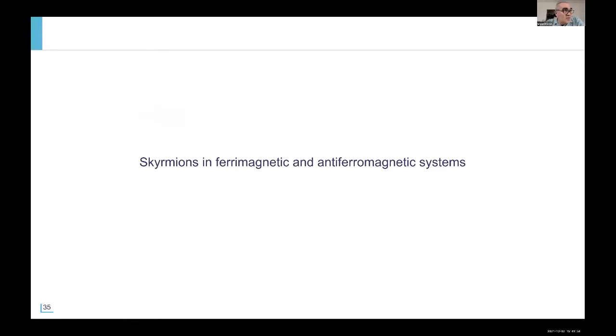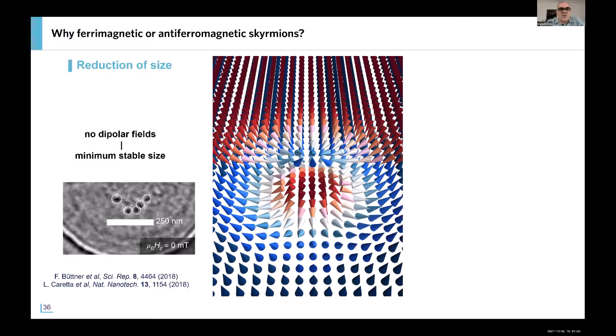Okay, so this was for the ferromagnetic experiments and also for the improvement of the motion, but then there are also some very interesting things to do in systems with cancelled magnetization, which can be ferrimagnetic or antiferromagnetic systems. Why is this important? Because, as I said, the dipolar fields between layers can make this hybrid texture, but also dipolar fields lead to an increase of the size of the skyrmions, and it is predicted that the minimum size will be obtained in systems with very small or compensated magnetization. This is one effect of the dipolar field.